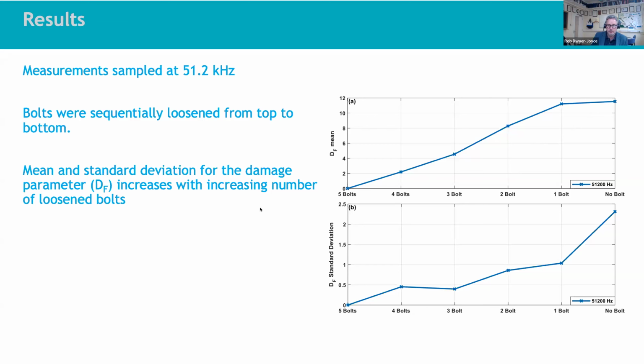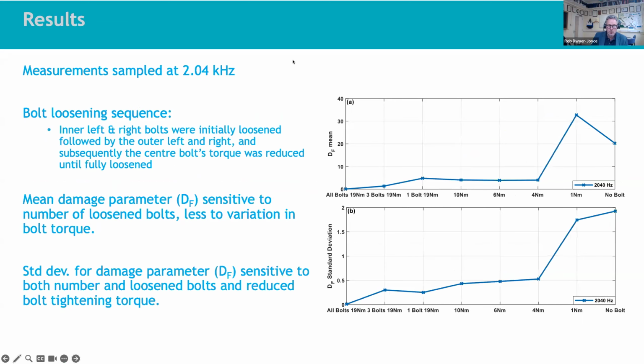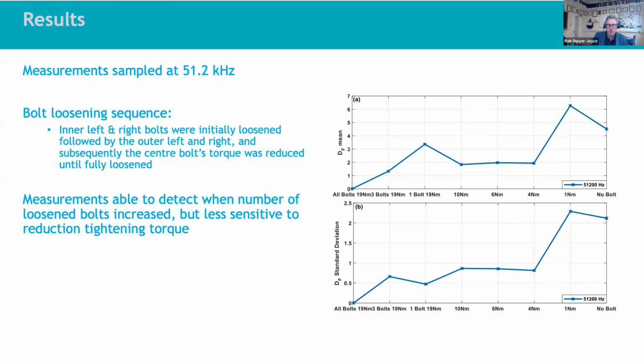And then the other sequence was that the inner left and right bolts were loosened, followed by the outer left and right, and subsequently the center bolt's torque was reduced. So it's 3 separate cases in there, and we could look at how this damage parameter was changed by the loosening. We could predict that as well. These are measurements at 50 kilohertz.